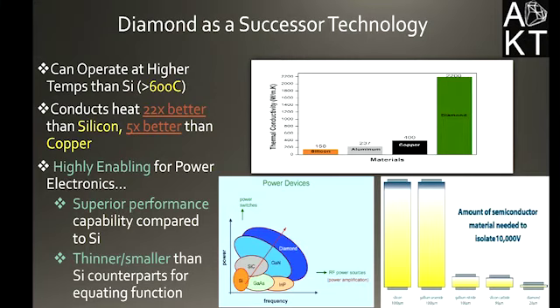So in terms of the performance, there's a critical need. In terms of the cost, there's a critical need. And in terms of the environmental and sustainability standpoint, there is a critical need. So one such material, which has long been held as a successor technology to silicon potentially, is diamond, because diamond can operate at much higher temperatures than silicon, over 600 degrees C. Diamond's performance does not degrade. It conducts heat approximately 22 times better than that of silicon, over 5 times better than that of copper.